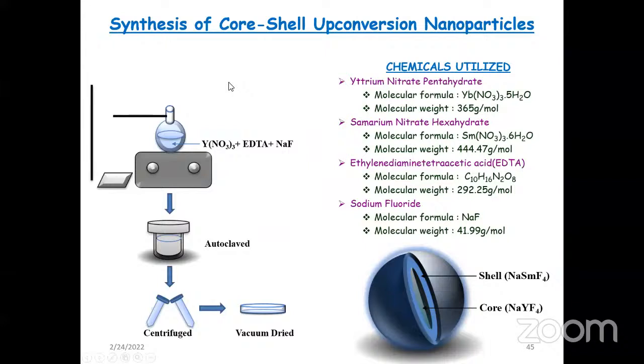We have considered a core-shell upconversion nanoparticle based on lanthanides, wherein we have taken sodium yttrium fluoride as the upconversion nanoparticle. Initially, we formulated sodium yttrium fluoride as a core material, for which we took yttrium nitrate in combination with EDTA and sodium fluoride at different ratios. We have mixed it, and then